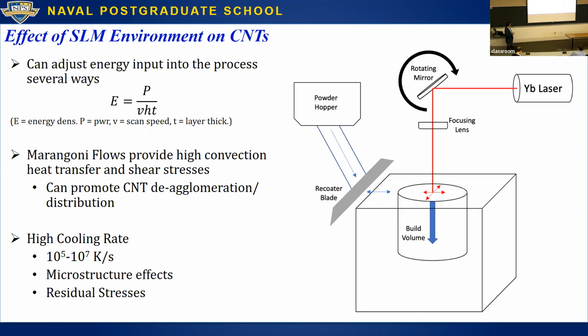These are some of the main parameters that people use when modifying the 3D printer. These are the main ones associated with the laser. There are other minor parameters such as the argon flow, the vacuum before it, the planarity of the substrate. But essentially, we look at the energy density, the energy that's being input into your metal to form a melt pool. And the melt pool is what's driving the solidification that eventually gives you a part. So we've got the power of the laser, the scan speed of the laser, and if you're familiar with welding, you know that how fast you scan across it can really impact your residual stresses. And then the actual layer thickness of the powder. That's set by the machine in terms of how thick you want your layer to be, which is basically just a blade coming across your powder.